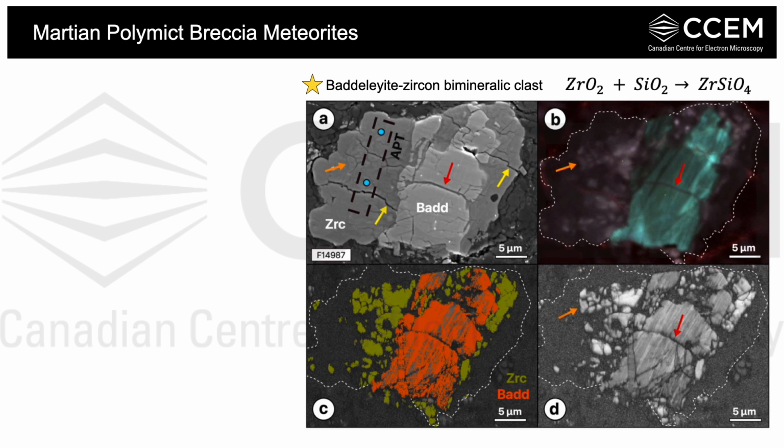And then we also see changes in lattice orientation. We can see this looking at our band contrast map. So band contrast is just a quality factor that describes the average intensity of our Kikuchi bands proportional to its crystallinity. And here we can see basically multiple generations of relic twinning.